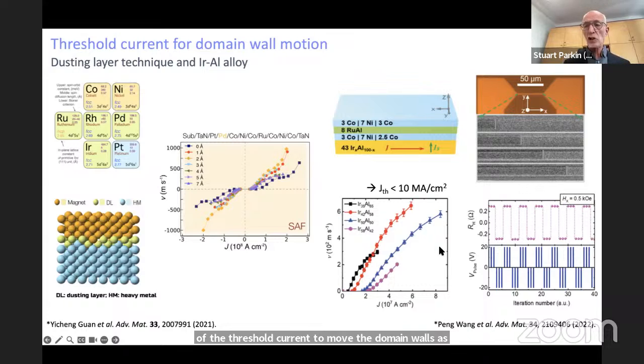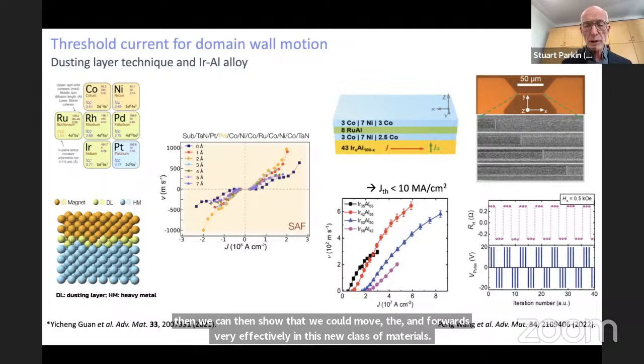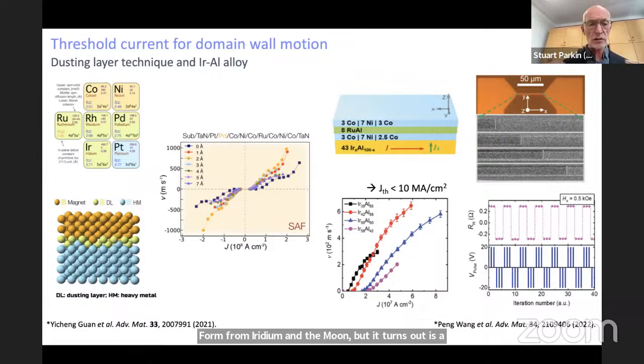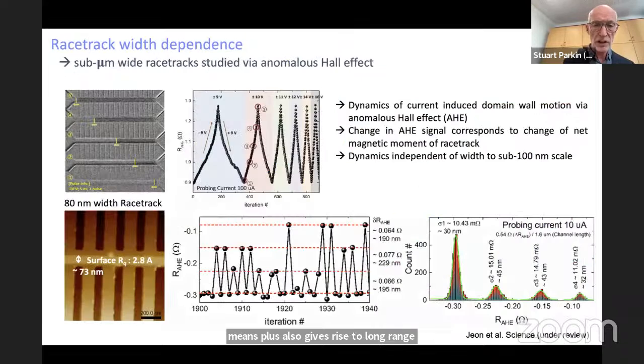And then we can show that we could move domain walls backwards and forwards very effectively in this new class of materials formed from iridium and aluminum. But it turns out it is a very large class of materials with the so-called L10 structure, which give rise to huge spin Hall effects from extrinsic means, plus also give rise to long-range oscillatory interlayer coupling, as we've demonstrated.